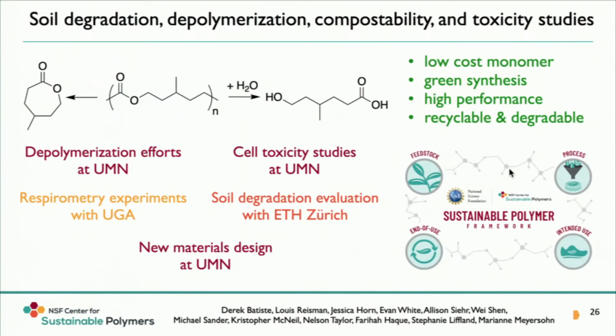And I'll finish by saying in the most recent work that we've done, we tried to build on this knowledge of, yes, methyl caprolactone can be made, we think, quite inexpensively. The polymers that we can make out of it, be they elastomers or plastics or polyurethanes or potentially adhesives and other applications, are high performing. We know that they can hydrolytically degrade. And a common question that we often get is, well, what about this degradation product, hydroxymethyl caproic acid? Well, we've been studying, for example, the cell toxicity of that material, and preliminary indicators are that it's not toxic at reasonable concentrations in cells.